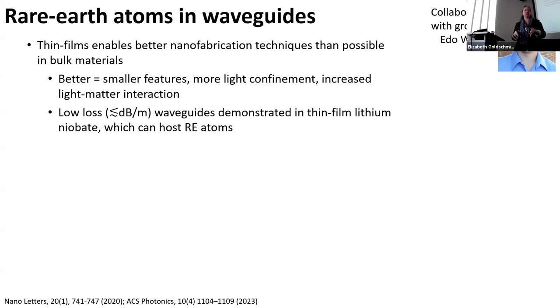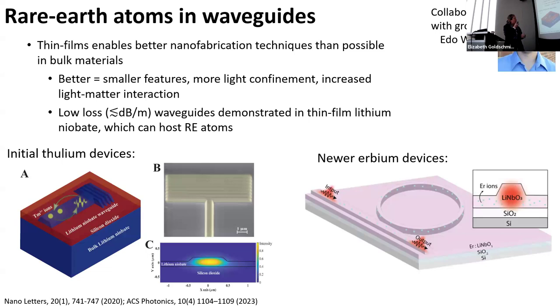And if you have a thin film that's submicron, sub-wavelength, you can get the tightest confinement that you can possibly get, right? Thin film lithium niobate has been commercially available for less than a decade, I think, now, or maybe a quarter of a decade. So it's become really popular, and it's known that lithium niobate is a good host for rare earth atoms. And so with Edo, we first started making these thulium-doped devices a few years ago, and then in my group recently, we've moved on to making erbium-doped devices.